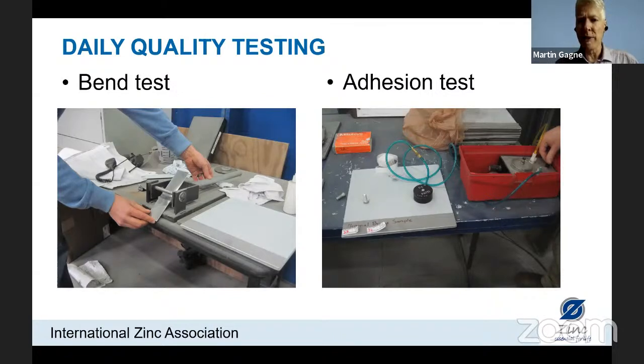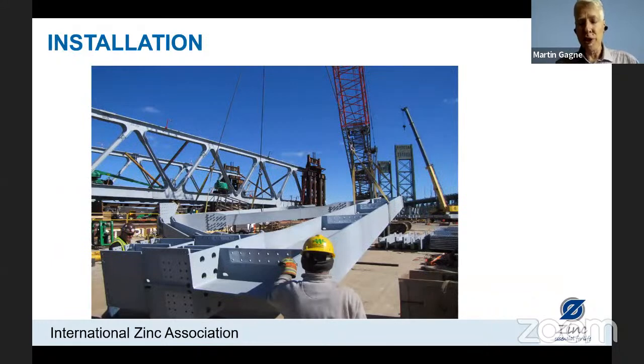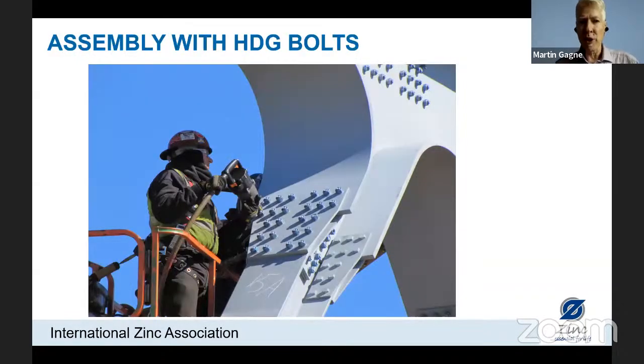So these tests are conducted daily. We can see there's a pile of samples in the right-hand side in the background there. So they're doing replicate tests in order to ensure the quality of the operator and the quality of the coating. So the steel was sprayed in a factory, then it was delivered to the site for installation. And we can see here one of the beams that was delivered. This was all assembled with hot dip galvanized bolts. And so again, we have zinc on zinc. We have no issues for bimetallic corrosion.